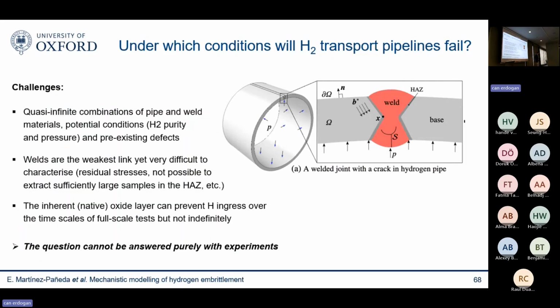And this is a very difficult question to answer experimentally for multiple reasons. First of all, because those natural gas pipelines have been there for decades, there's a quasi-infinite combination of pipe materials and weld materials. There are pre-existing defects that have been there through operation over decades, from corrosion, from in-service conditions. And also as an engineer, you have a quasi-infinite combination of conditions as well. You can choose to transport your hydrogen at any pressure that you want, at any purity that you want. So there are many, many conditions, so it's very expensive to test in the lab.